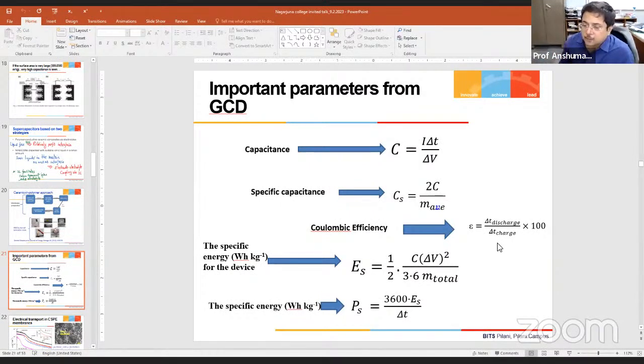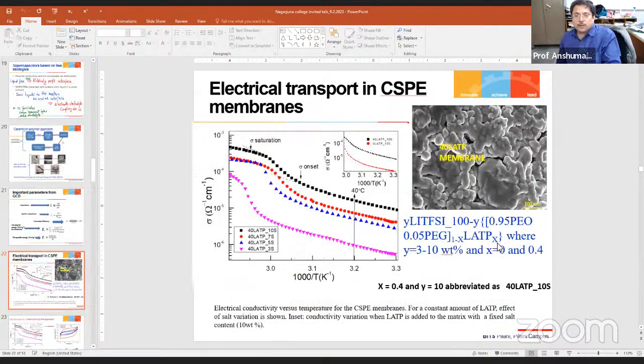Again, energy with respect to the mass. So the same formula, 1/2 CV square, but with respect to the mass of activated carbon on the electrode. Some people report with respect to the total mass. Some people report with respect to the activated carbon on a single electrode. But normally a good practice is that for the energy and power, one should mention with respect to the mass of the device, whereas specific capacitance is an electrode property, so it should be reported with respect to the mass of the electrode. Fine.